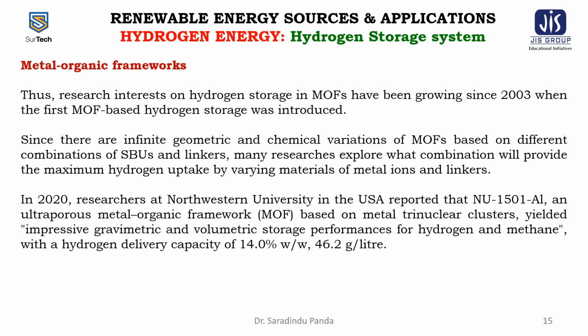In 2020, researchers at Northwestern University in the USA reported that NU-1501-Al, an ultra-porous metal organic framework based on metal trinuclear clusters, yielded impressive gravimetric and volumetric storage performances for hydrogen and methane, with a hydrogen delivery capacity of 14% and 46.2 grams per liter.